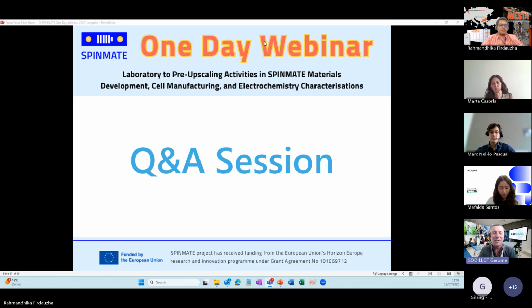So this is for the preparation, and then regarding the final drying step, actually it's not that different from acetone. It's quite easy to remove all the MEK, and we made some characterization to be sure that we have very low remaining amounts of solvent, below 100 ppm, even lower in certain cases. You just increase the temperature of your drying step a bit, and you can manage to dry out the MEK.